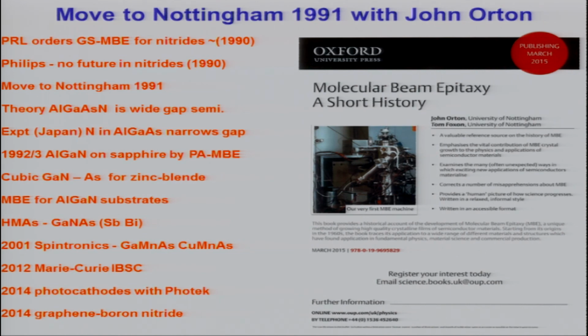And that's led also to the work on highly mismatched alloys with collaborators here in the USA and back in Curie. Around about 2001, we started the work on spintronics, and Richard is also here somewhere in the audience. Most recently, the gallium manganese arsenide, we managed to get to about 200 Kelvin with a combination of careful growth and in situ annealing studies, but there's no way that we're going to get to room temperature. But this new material, copper manganese arsenide, which is antiferromagnetic, has an anneal temperature well above room temperature. So it may well turn out to be a very useful material.